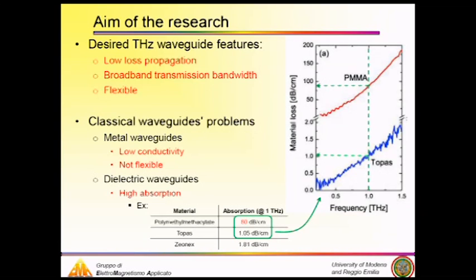Here I show you the typical absorption spectrum of two kinds of polymers. PMMA, polymethyl methacrylate, the red curve, is very much used in the infrared spectral region, but as you can see, at 1 Terahertz it has an absorption rate of 80 dB per centimeter. Topas or Zeonex, which are two of the most transparent polymers used nowadays for Terahertz frequencies, still have 1 dB per centimeter, making it quite complex to have long distance propagation with these solid core fibers.